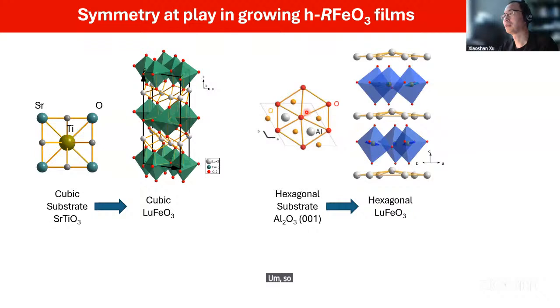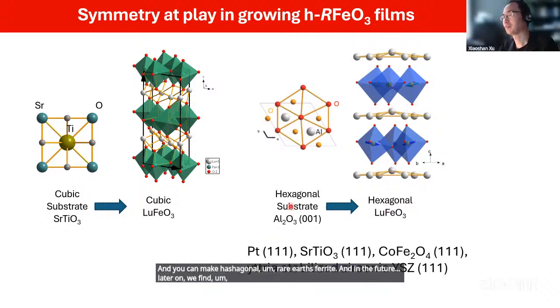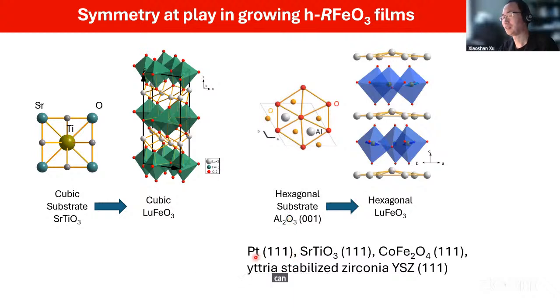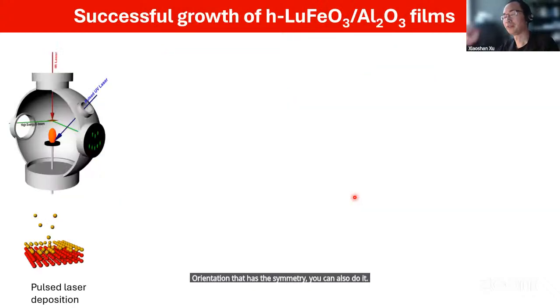So the trick we play is to grow this as a thin film on top of a template. If you choose a template that has hexagonal symmetry, like this aluminum oxide, you can make hexagonal rare earth ferrite. And later on, we found it does not have to be aluminum oxide. It can be platinum, strontium titanate, cobalt ferrite and YSZ. But all of them actually are cubic materials. But if you choose a certain orientation that has the symmetry, you can also do it. Okay, and this is how we do it.